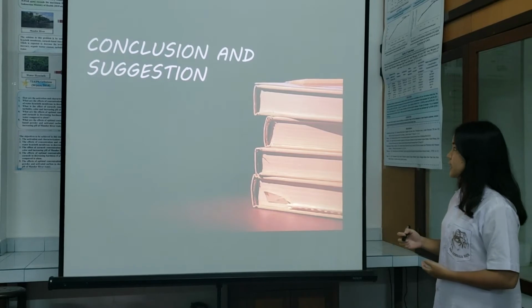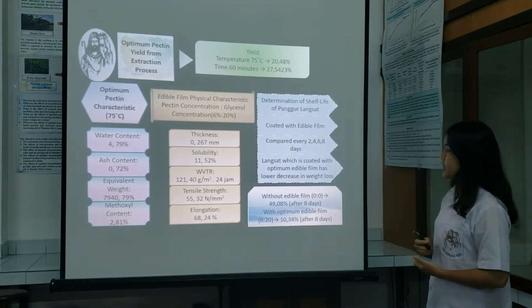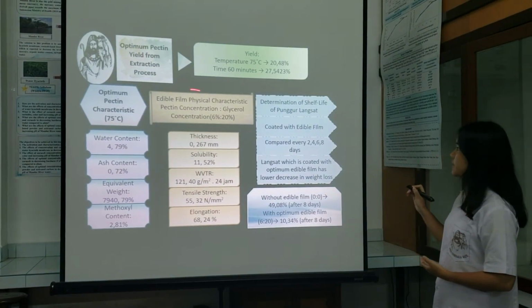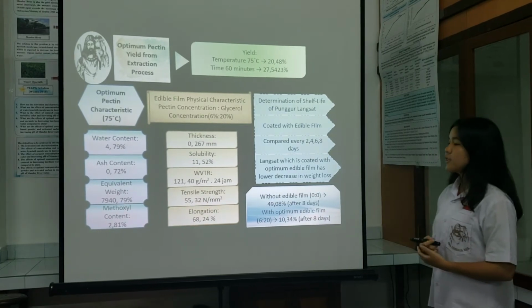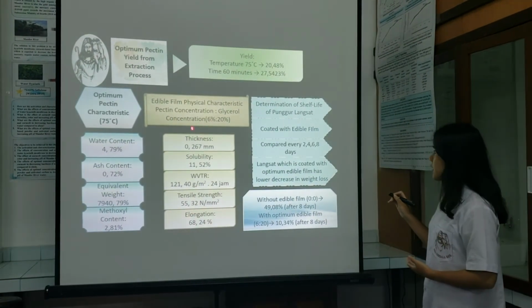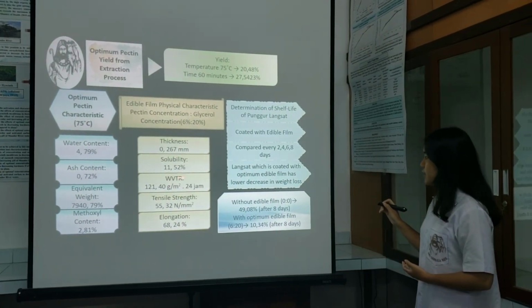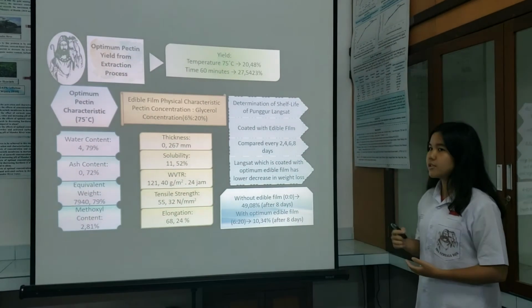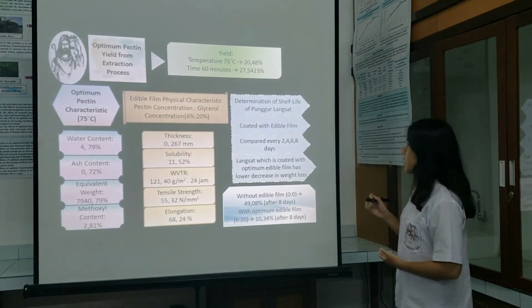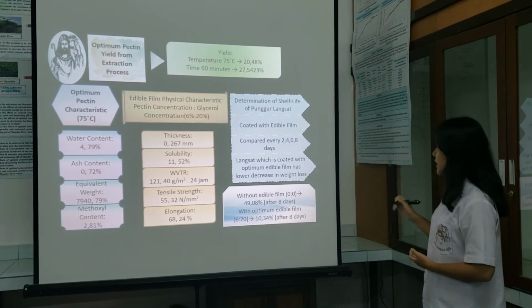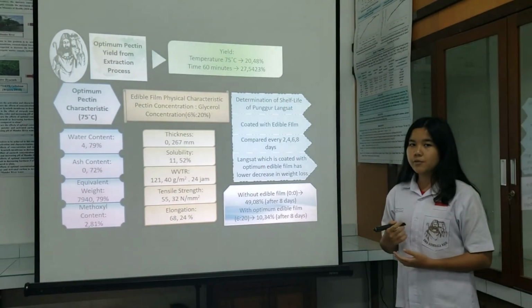It can be concluded that the optimal edible film variation is obtained from the variation of 6% pectin, 20% glycerol, with the physical characteristics of thickness, solubility, WVTR, tensile strength, and elongation as follows has met the standards. The optimal edible film is then applied to Punggur Langsat and able to increase the shelf life of Punggur Langsat up to 8 days.